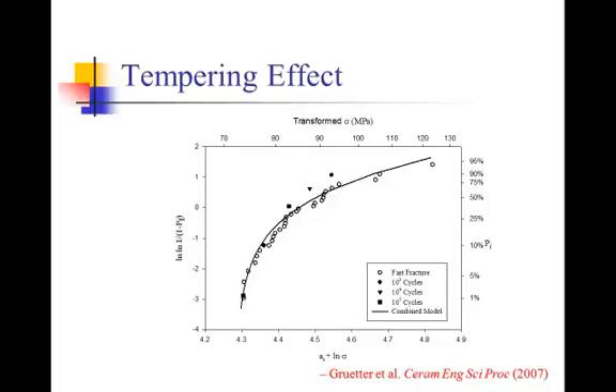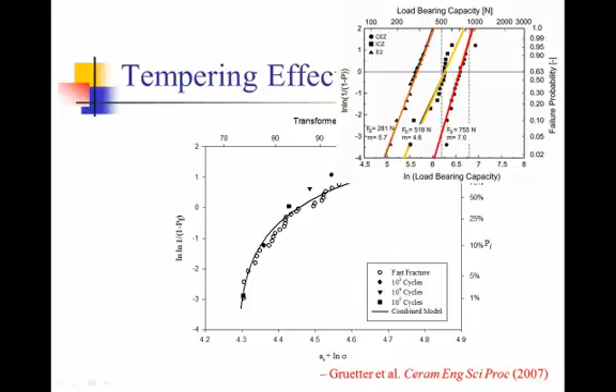And this shows the effect on a Weibull chart that tempering has. Just to remind you, here's what the Weibull chart for non-tempered materials looks like. After we do the transformation to the axes, this strange log-log transformation, we expect to see a straight line. But after we temper a ceramic material, we no longer have a straight line. We have this curved behavior. And that will be curved because there's a threshold stress below which the material feels as if there is no stress mechanically being placed on it, and the cracks don't grow at all. And so we have a point at which the probability of failure suddenly drops off to 0% probability of failure at all stresses and loads